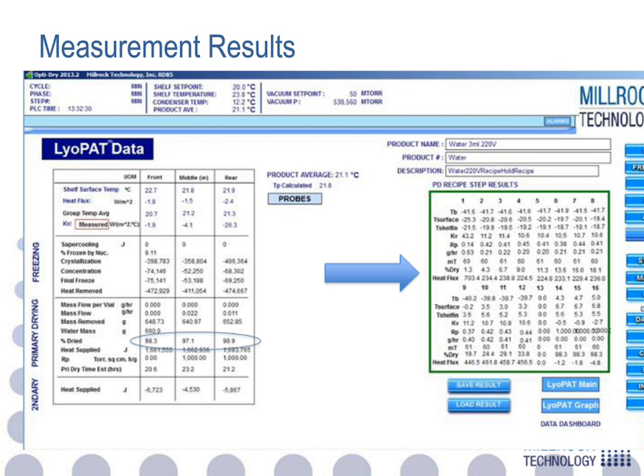You'll notice in this case it was 98%, 97%, 99% essentially of the measurements. They're not always that close because we're looking at local events that take place, and they're not always the same. We also measure the cake resistance in torr square centimeter hour per gram. And by the way, all this data is saved and can be graphed and reviewed. We estimate the primary drying time, but I'm going to be right up front and say our calculation there is terrible, that we've got to improve.